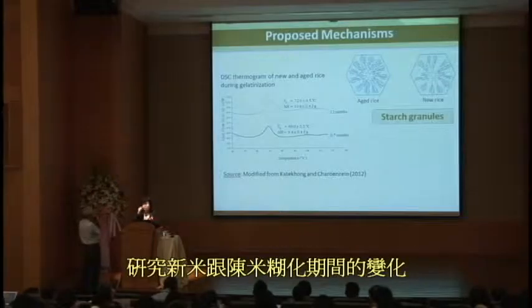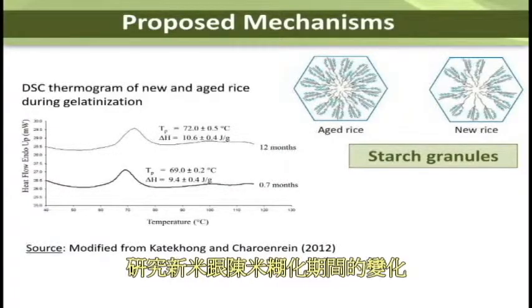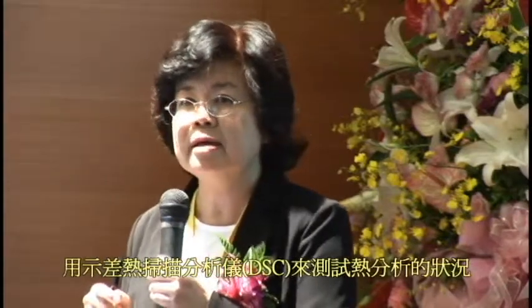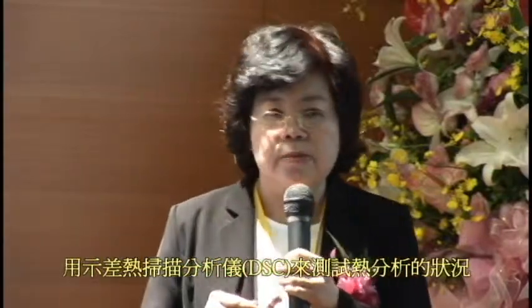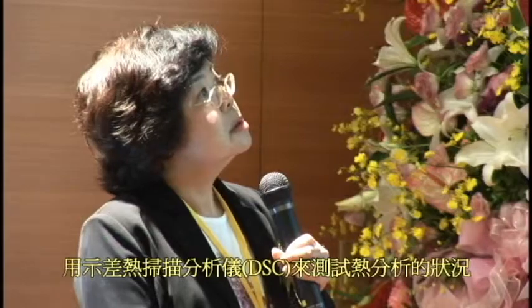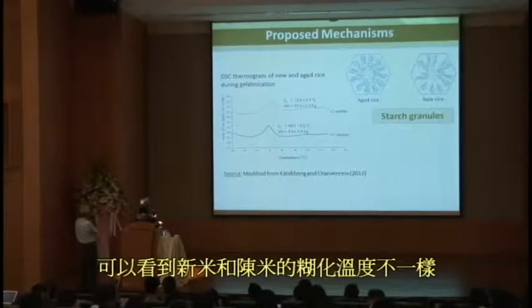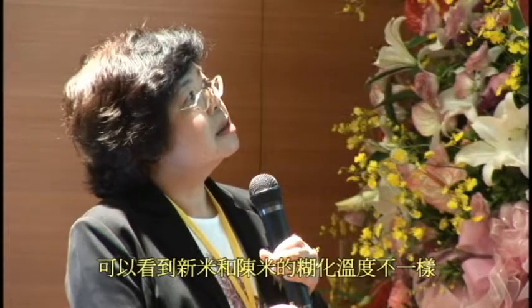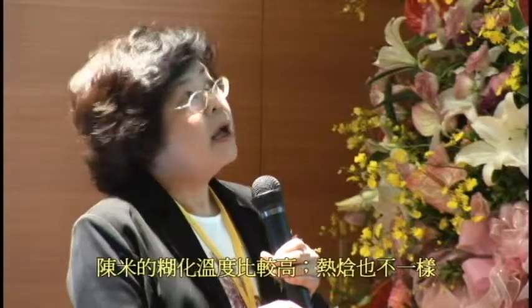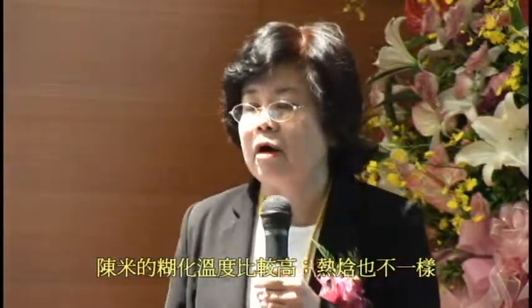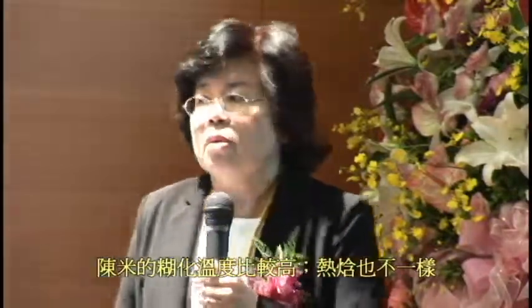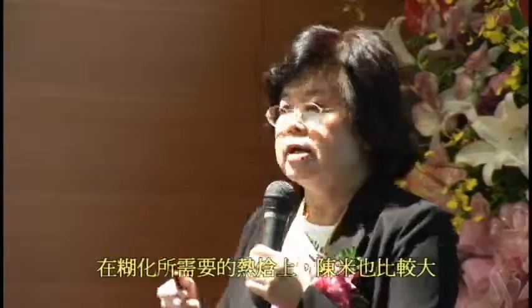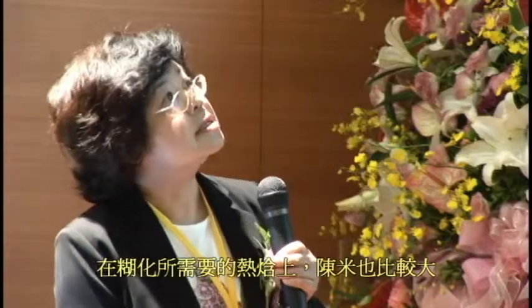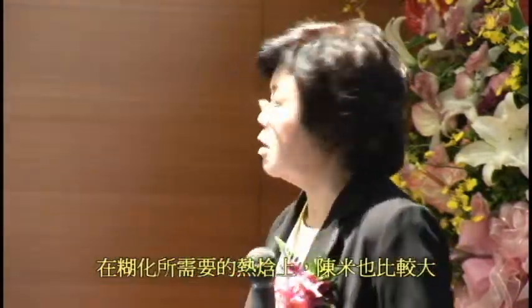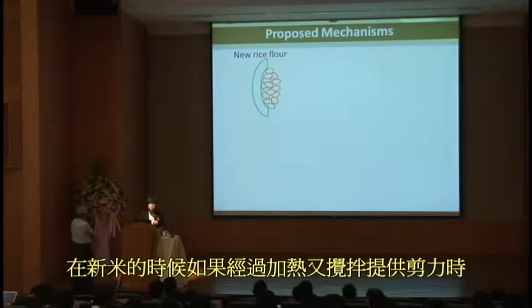Another point is we also looked at the gelatinization of the rice with different storage times using a differential scanning calorimeter, or DSC. And this is the thermogram of the aged rice, 12 months, and the new rice. You can see that the gelatinization peak of the new rice is at a lower temperature than the aged one. And besides that, delta H, which is the enthalpy of gelatinization, is increased. So we think that the crystallinity of the aged rice is increased, and this can be the formation of hydrogen bonds in the aged rice. So this is what we think happened during the testing property determination.